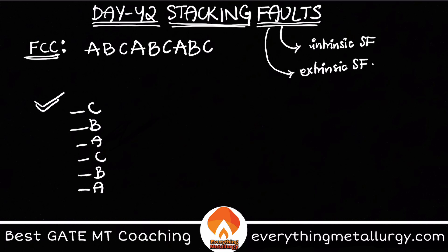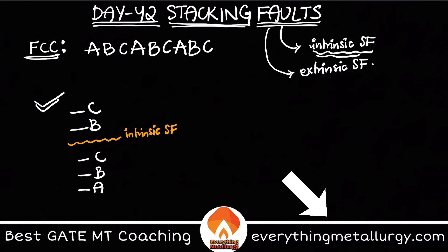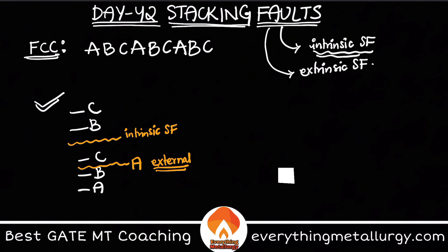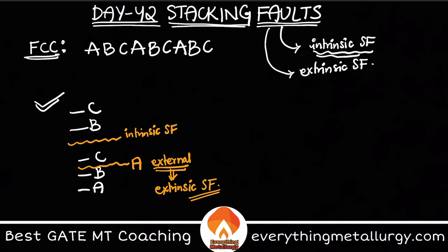Intrinsic stacking fault is nothing but the removal of any internal sequence. Let's say I am removing a layer — some layer 'A' should be there but it is missing, so an intrinsic stacking fault is formed. Whereas extrinsic is the addition of a new external layer coming in between the existing ones. This is the basic definition of stacking faults — determined by either adding or removing an existing stacking sequence.